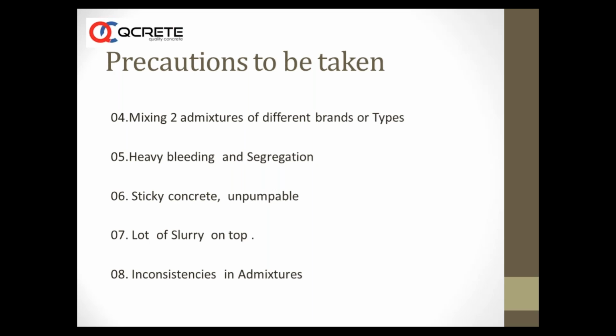So we need to control the admixture dosage, and we need to do one or two more trials, probably with increased sand content or something like that to control this. Sometimes we end up with sticky, unpumpable concrete - mostly related to the properties of the admixture. Sometimes you can rectify it by increasing the sand content, but generally we can change the admixture if it is very sticky and unpumpable.